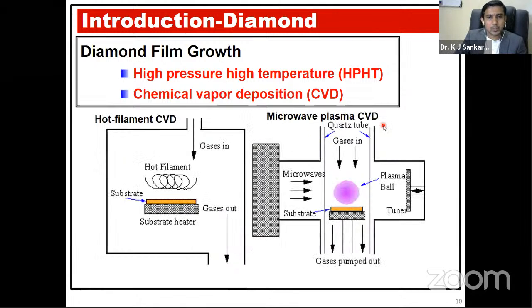There are two well-known CVD methods, the hot filament CVD and the microwave plasma CVD. Coming to the hot filament CVD, you can see the hot filament here, which is a tungsten filament that can be heated to more than 1000 degrees Celsius. Once you pass the gases, this high temperature filament can emit some electrons that react with these gases and make a plasma, so that it can make a film on the substrate. This is the substrate heater and this is the substrate, so the diamond can be grown on the substrate.